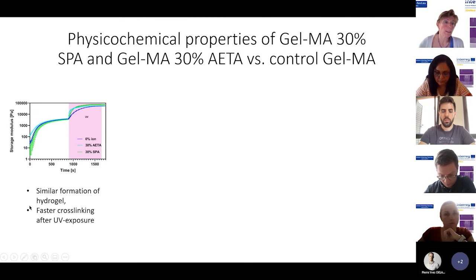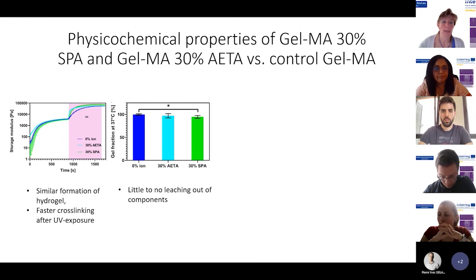And then we compared, for example, the storage modulus, and we saw that in the three conditions there is a similar formation of the hydrogel, although the gels containing the ions have a little faster cross-linking after UV exposure.